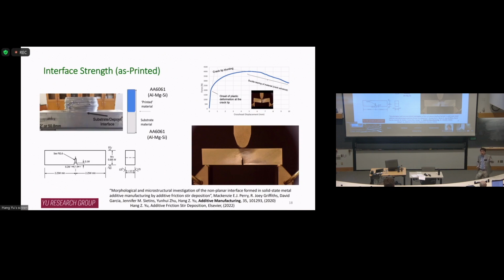And then we cut a beam in the center. So I have a beam in the center here, right? So now my interface becomes the center of the beam. Then we generate a notch here and get a pre-crack by fatigue. We do a single edge notch bending test here. We want to see, under this 3-point bending condition, how the crack propagates in the center, which is essentially my interface between the deposition and the substrate. So this is what we get.